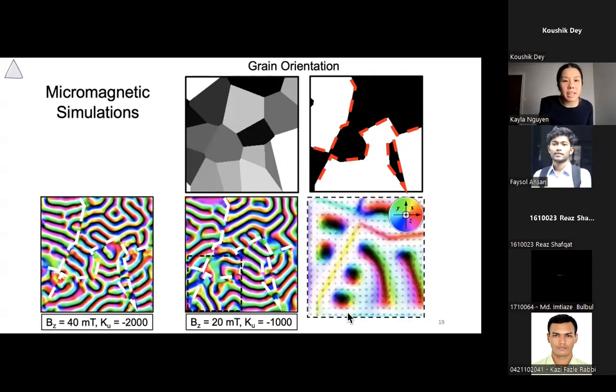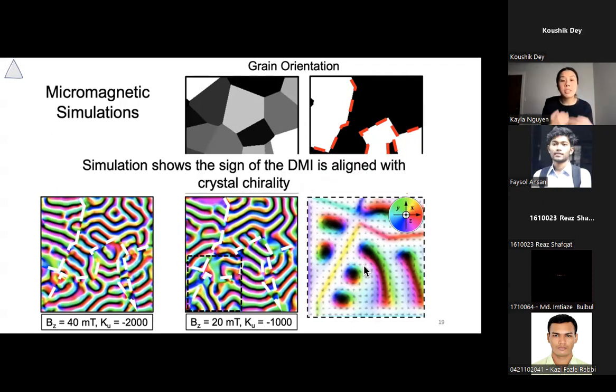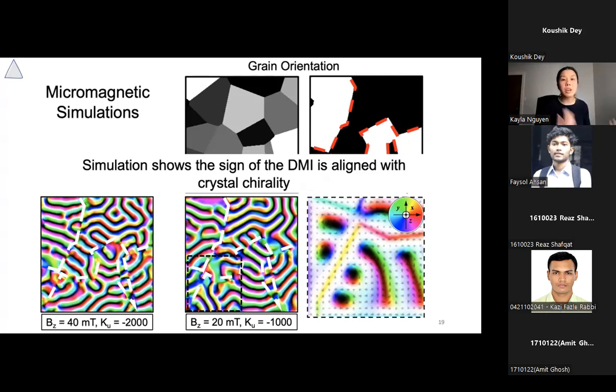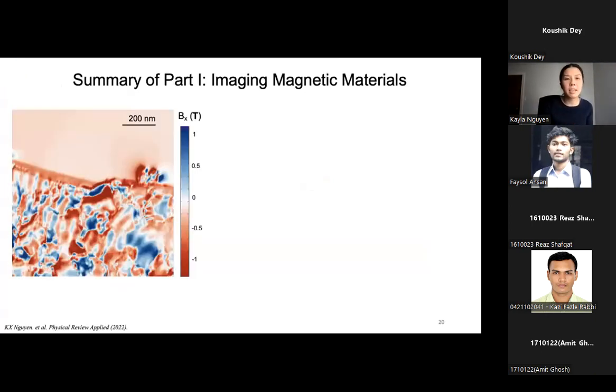And what we find is that within the grain boundaries here, because these crystals have different crystal chirality in our simulations, we find that this grain is rotating counterclockwise, and this grain here is rotating clockwise, and the bottom grain here is rotating counterclockwise. So simulation supports our results and shows that the sign of the DMI, or the Dzyaloshinskii-Moriya interaction, is aligned with the crystal chirality. So in summary, we can image magnetic textures of B20 iron germanium.